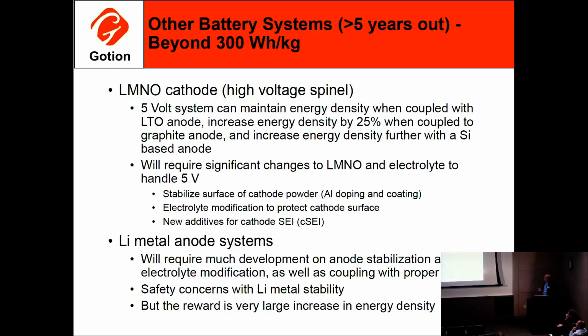And so there's two basic systems that are fairly early on, but that we're looking at. That's the high voltage spinel LMNO. That's the prototypical 5-volt material. It's probably about 4.8, but people call it a 5-volt material. So if you couple that with, say, an LTO, you probably say your energy density is about the same as a standard NCM material with graphite today. If you couple this 5-volt material with a graphite material, you can get 25% more energy density. And if you couple that with silicon, you take another increase in energy density. So this is really something that's going to be important in the future.